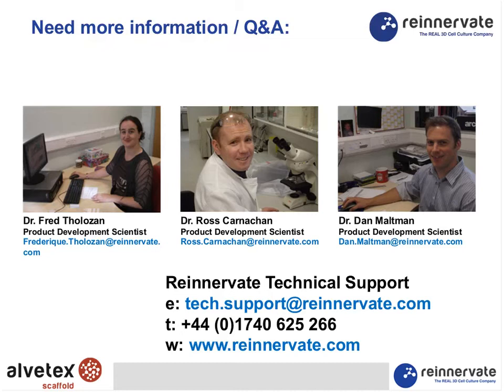Yes, hi. Somebody's just asked if Alvetex is chemically resistant. The answer to that is yes, it is, due to the actual cross-linked nature of the polystyrene, as I discussed in the presentation. But people must be aware that any organic solvents used, or any good organic solvents of polystyrene, generally will swell the actual material itself. It will just change in size.